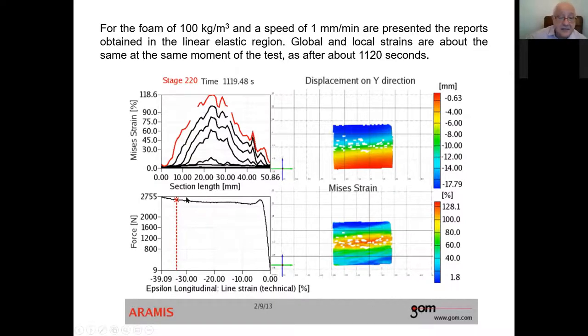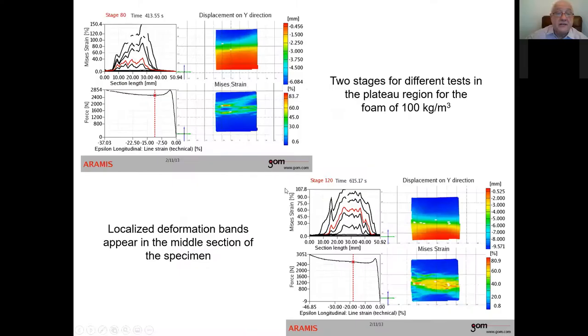But essentially, towards the end of the test, as you can see here, you are going to have a middle deformation band and a local strain which is practically equal to the global one. So the important thing I want to underline is that you can have very precise measurements of local strains, following what is going on at different stages. And here, at the end, for the same 100 kilogram per cubic meter density, you see this kind of localization of the deformation bands.